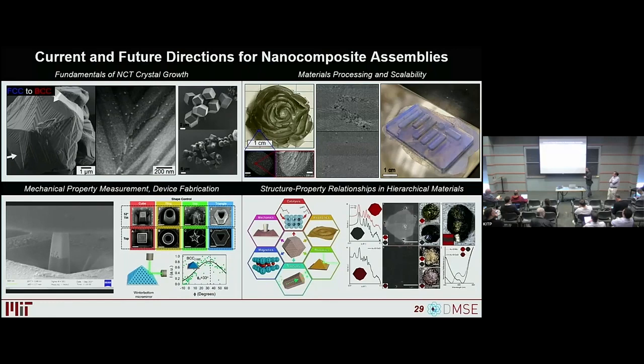In terms of controlling the size, we basically have not found a cooling rate where we don't form crystals. I can take something that's at 80 degrees C, pop it off of the heat block and onto the bench, and come back 2 minutes later, and I'll have a nice Wulff polyhedra. In terms of actually controlling that size, we can give you basically a controlled size range as a function of those variables I mentioned of cooling rate or concentration, but it's always a spread. And so this is why we looked into the density gradient centrifugation, so we could separate these things out. I think if we really wanted to nucleate and grow low dispersity systems, we need to do those studies that I mentioned of really understanding crystal nucleation and growth a little bit better.